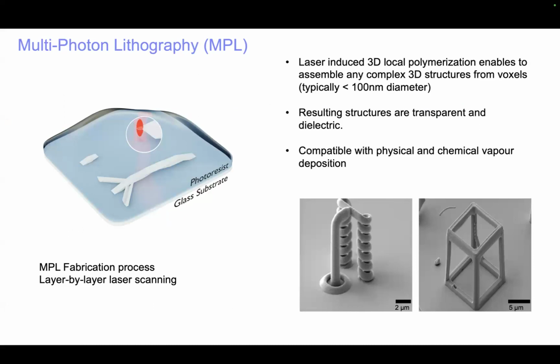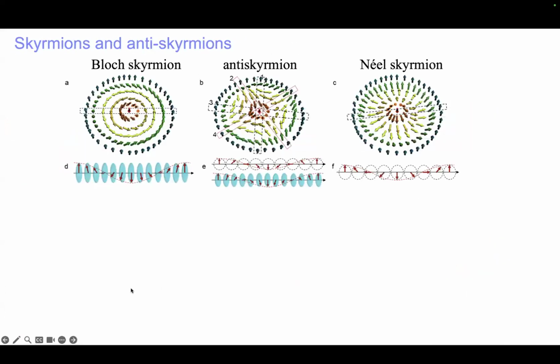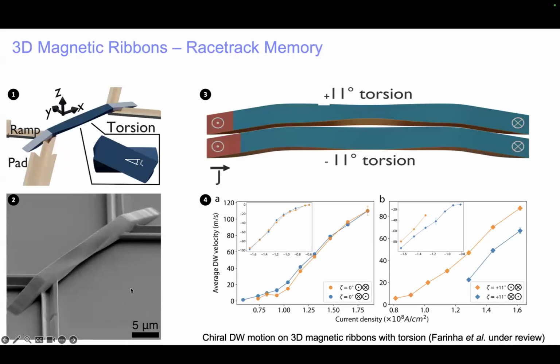And the idea is you build a scaffold on which we then place the racetrack by sputtering. And this is what we did here. You can see an image of the polymer scaffold which we've designed so that instead of having a flat surface, it has a curved surface. And we were exploring the interaction of three-dimensional geometrical curvature, chirality, and the chirality of the domain walls that I mentioned before. And we can see that the geometrical and spin chiralities can oppose or add in interesting ways to increase or decrease the domain wall velocity. So we have a paper on this under review.